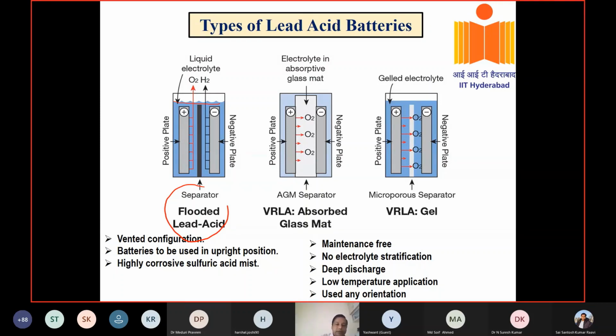And the other one I told you, the valve regulated lead acid battery. This was evolved during the 1970s. In a valve regulated lead acid battery, they use a separator called absorptive glass mat, or there is another valve regulated type called gel, where they use a gel electrolyte. What is gel electrolyte? This is made up of silica. This is a very good separator. It can soak a lot of electrolyte. It is more than 70% porous.